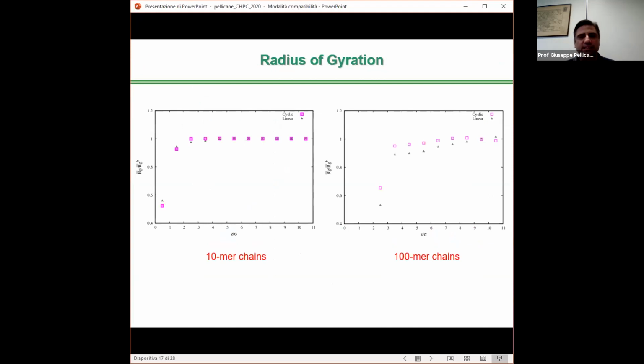In this slide, we look at a simple parameter that is directly linked to polymer flexibility and conformational entropy. This parameter is the radius of gyration, and we calculated it as a function of the distance from the interface. Even in this case, there are some evident differences between short and long chains. The radius of gyration gets smaller as the interface approaches, which means that the polymers get more folded and lose conformational entropy in both cases. However, if you look at the panel on the left, you see that for short chains the trend is very similar, and the cyclic polymers get just a bit more folded than linear polymers. While for long chains, look at the panel on the right, the greater linear polymer flexibility allows them to fold more efficiently at the interface in comparison to cyclic polymers.